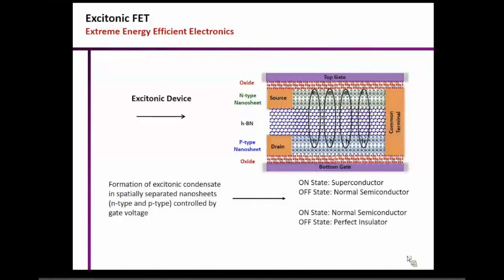Another idea that is more ambitious, which currently we are trying to explore, is the excitonic field effect transistor. This is where I call it extreme energy efficient electronics, because one of the holy grails of science is if you can make a room temperature superconductor, right? To some extent, if you can create excitonic states inside a material, then you can have a Bose-Einstein condensate, which will lead to this superconducting phase transition. Now the problem is that in a normal material, this electron-hole pair is easily recombined, and the lifetime is very short. But if you can physically separate these electron and hole pairs, but still keep their Coulombic interaction, you might be able to create excitons which can exist for a longer period of time, and they have much more probability of forming this excitonic condensate, giving you this phase transition.